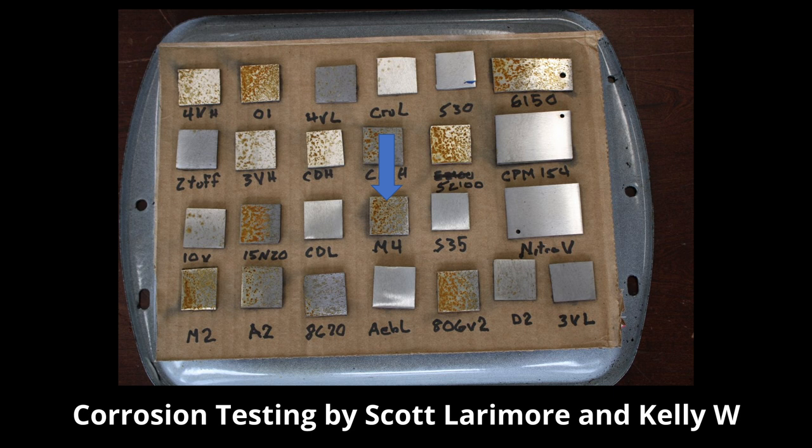But CD#1, Z-Tuff, 3V, they all had little or no corrosion in this test. The CD#1 actually did slightly better than Z-Tuff. I don't know if that's because its chromium is a little bit higher or if it's just the randomness of this test, if the Z-Tuff coupon wasn't finished quite as well or if the Z-Tuff coupon got a little more rain out in the elements.